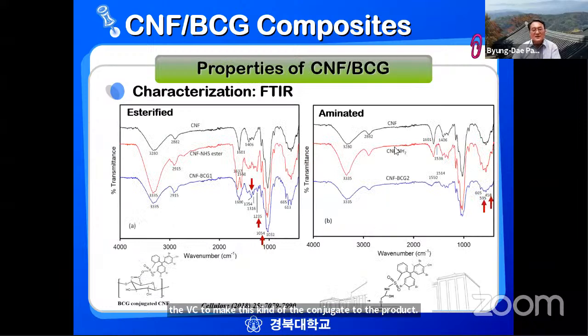And then we checked whether the reaction was properly done or not. And this is the esterified CNF and the control. The intermediate product, this is CNF with the BCG. One is the CNF with the esterified CNF, and then this kind of product. And then we have new peaks here, the conjugation of CNF and the BCG conjugation here and here. These are the new product.